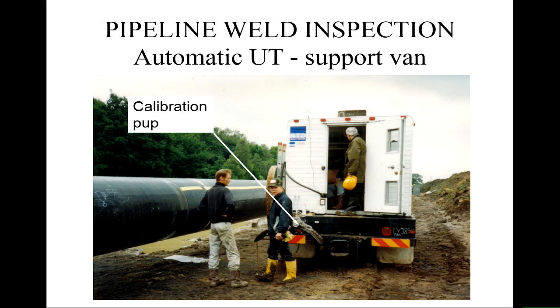Now, doing it on site requires one extra thing that you do, because these ultrasonic systems and the speed of sound in material is temperature dependent. So you have to calibrate and set up the machine on the site on the day you're doing the measurement. So you have this thing here, this is a calibration pup. So this is a piece of the same steel that you're making the pipe, with known thickness and known curvature and known defects, may even have a weld in it of known properties that you've already measured before, and you set the machine up using that to start off with before you make realistic measurements in the field. So calibration of these detectors is very, very critical, and it has to be done under field conditions. So that's another part of the process.